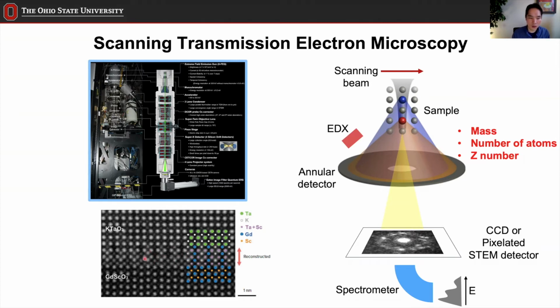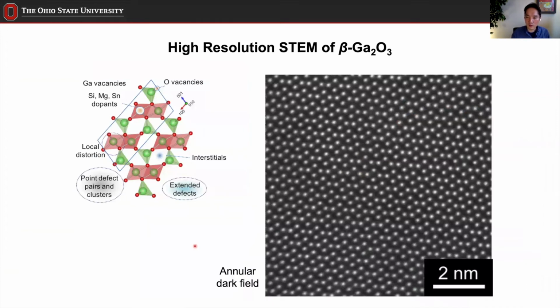the interface. Now, such information is something that you cannot get with X-ray, because the X-ray beam is so large that the whole information is averaged. So you don't get any localized information. But using this annular detector and the scanning electron beam, we can get all the details of what's happening at the atomic scale.